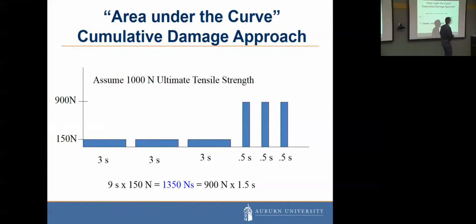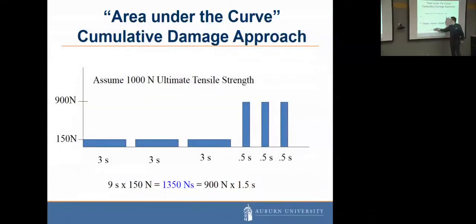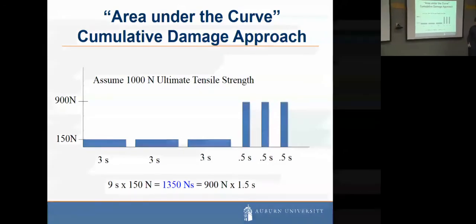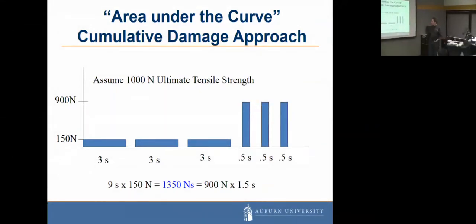People in the past had used an area under the curve technique for developing cumulative damage assessment, cumulative risk. They asked how much loading times how much of a load. So this is 3 seconds of loading at 150 newtons. You do that three times. Or you could do 900 newtons worth of load times 1.5 seconds. In both cases, you would end up with 1,350 newton seconds worth of load. So those would be equivalent using an area under the curve technique.